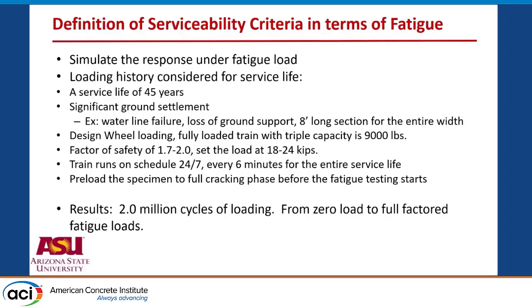The load would be defined in the context of the train car being fully loaded to 3 times the capacity, and then running it every 6 minutes, 24/7, for 45 years. That ends up to be about 2 million cycles. So we have to test these sections at 2 million cycles of fatigue to the load which carries that specific service level loads. So that was the basis.